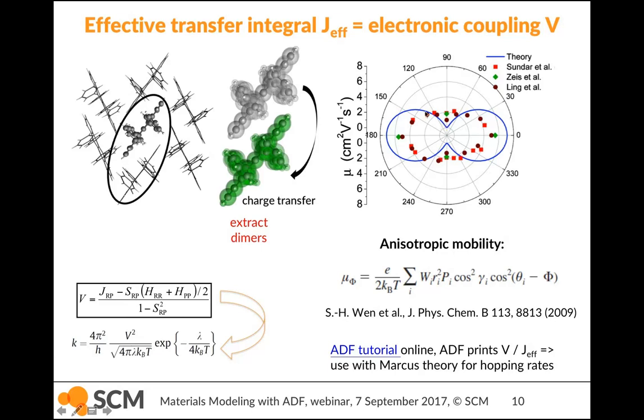And so in blue here, this is the theoretical charge mobility on a polar plot, and in general that corresponds reasonably well to the experimental results. Usually you find that you're within, let's say, 20 to 30%, and what you describe really well here is the anisotropicity. So the mobility is really high in this direction, but it's less high in the other direction. I don't know if you actually copied the crystal structure picture okay here.